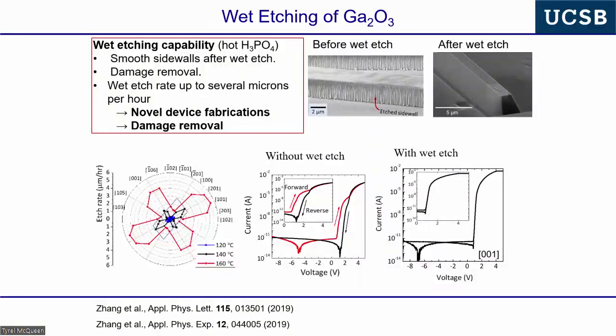And then when we do wet etching, it turns out that for gallium oxide, there's probably many other chemicals, but we use hot phosphoric acid. And then we look at the temperature dependence in the etch, and we look at the crystallographic orientation of the etch rates in these wagon wheel patterns. So we can get controllable etch rates up to many microns an hour. So this is totally acceptable for mass production and fabrication. This is a totally acceptable process.